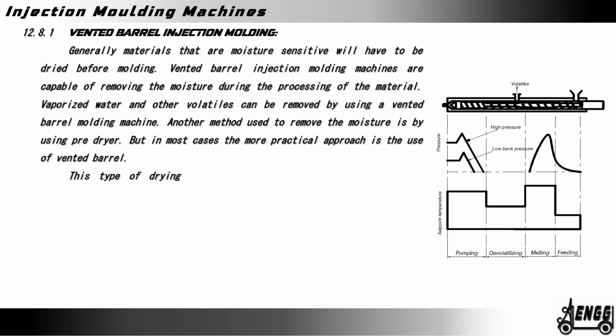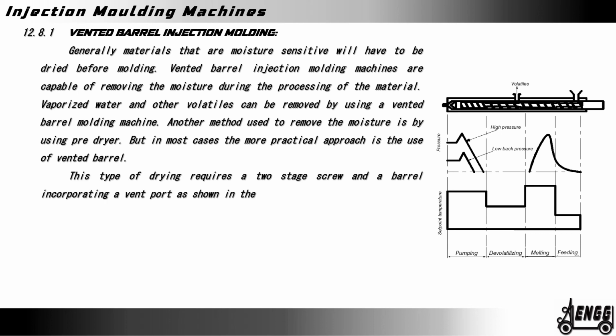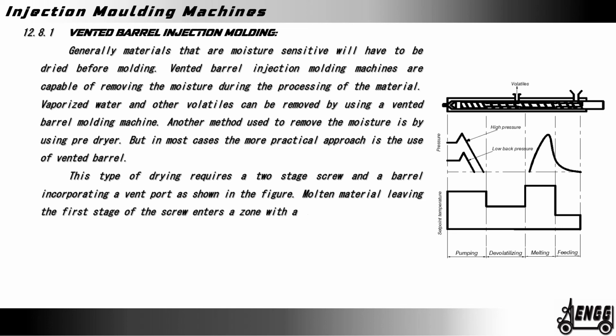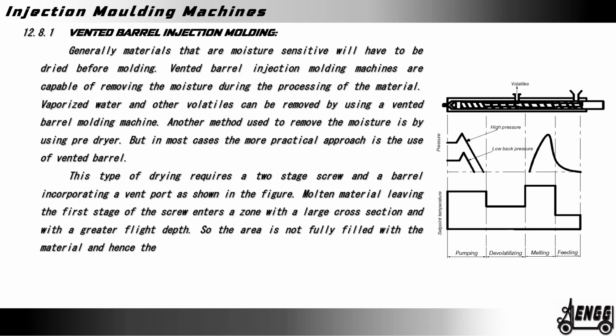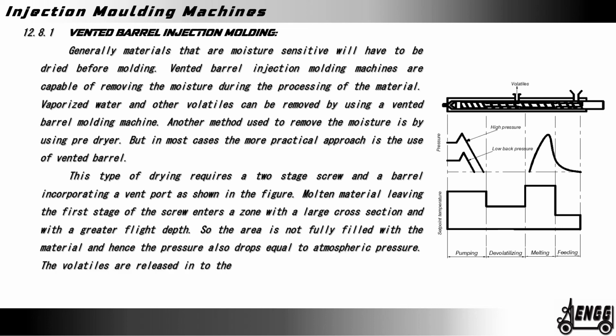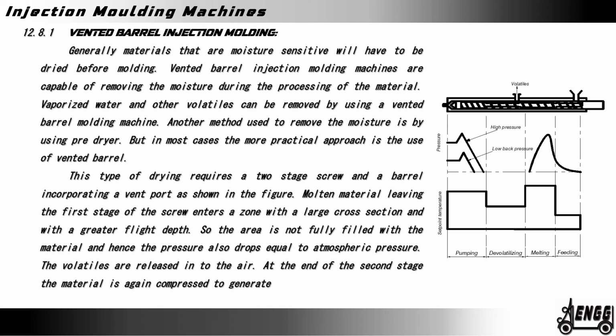This type of drying requires a two-stage screw and a barrel incorporating a vent port, as shown in the figure. Molten material leaving the first stage of the screw enters a zone with a large cross-section and a greater flight depth. So the area is not fully filled with the material and hence the pressure also drops to atmospheric pressure. The volatiles are released into the air. At the end of the second stage, the material is again compressed to generate the pressure necessary for flow through the non-return valve.